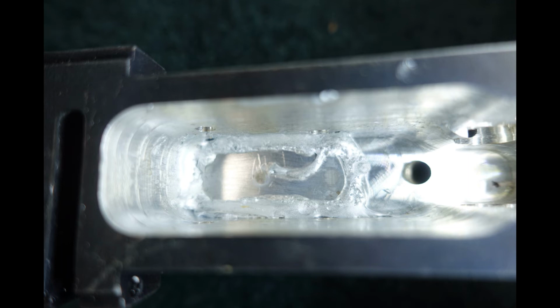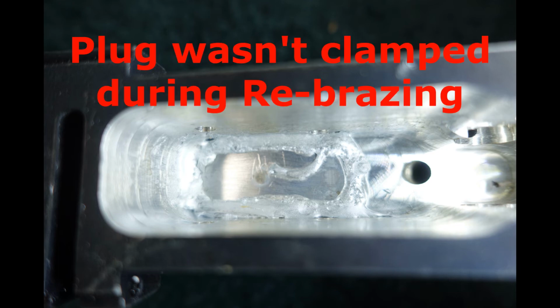Here's some bonus footage. When Racer X and I saw the plug in that last coupon and how difficult it was to pound it out, we realized how strong this brazing rod was. And we decided not to TIG weld my final project, and we decided to use the aluminum brazing rod. So what we did wrong with that last coupon was, one, we had the heat on too long and all the aluminum oozed out. Plus we didn't have that plug clamped in properly, and it kind of floated up out of position.